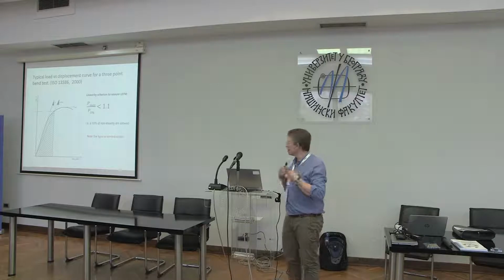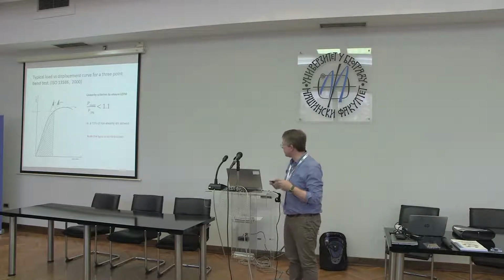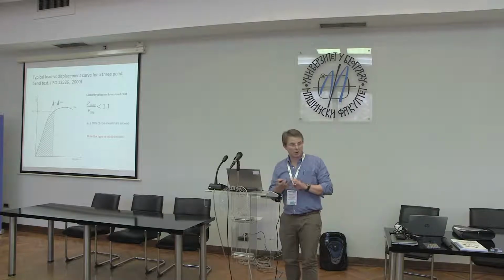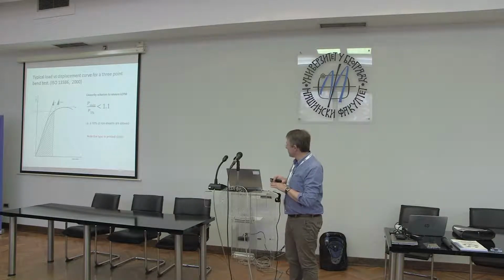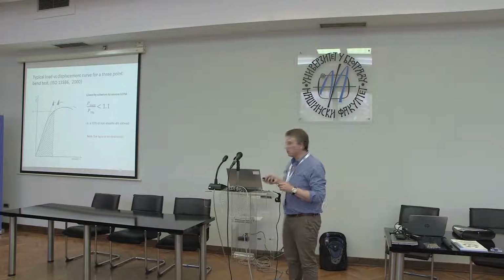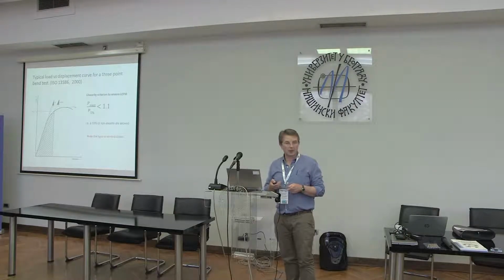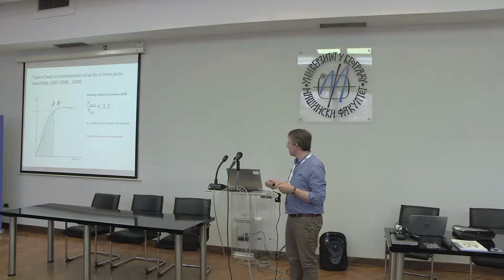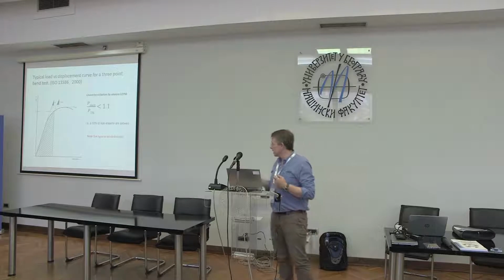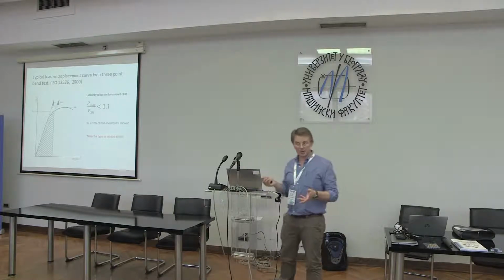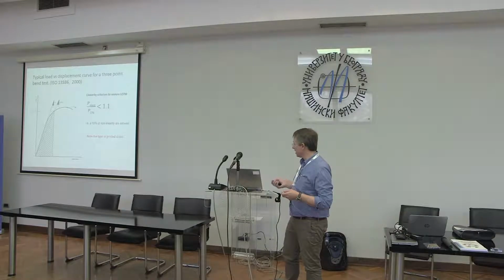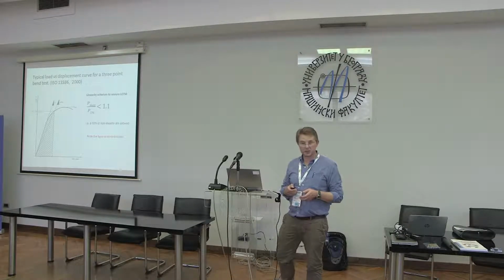So let's just have a quick review as to what we do with this information. Of course, we apply SENB or compact tension specimen. We load quasi-statically. The rate is specified. We run that until the crack initiates and the forces tail off. The specimen should initially be linear, and then we have non-linearity, a maximum force, and we control the amount of non-linearity allowed in the specimen. So this allows us a non-linearity of about 10% in total.